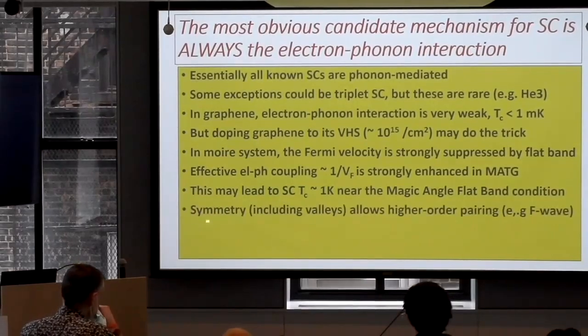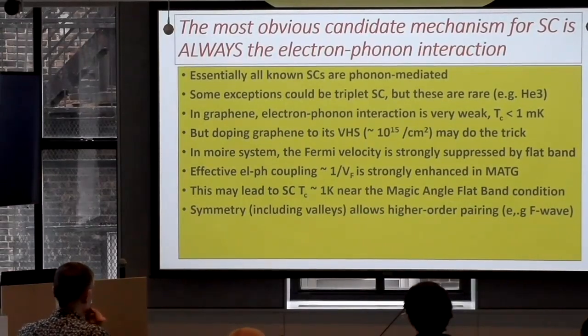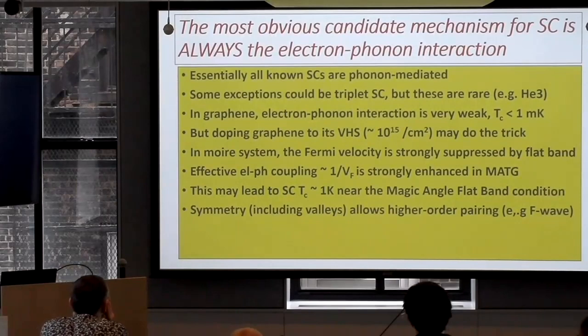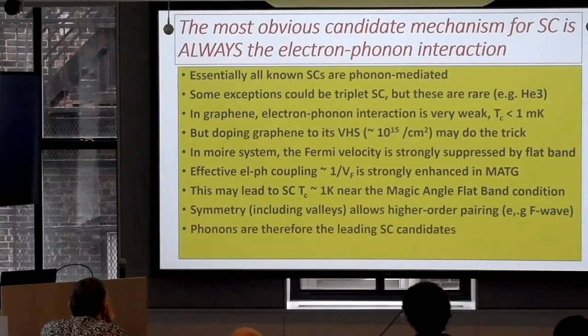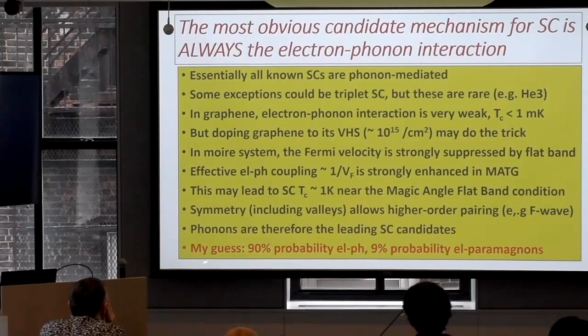Now, since you have symmetry, including valleys, you can have higher order pairing. Normally, electron-phonon interaction just gives s-wave. But here, as I'll show you, there could be degeneracy between s-wave and f-wave. The original argument was you cannot get higher order superconductivity, but now we know that it happens, okay? So it's a candidate. My current belief is that there are some situations, in particular Bernal bilayer graphene, where it probably is electron paramagnon, but the rest are electron-phonon. I'm not very happy with that. Two mechanisms come in. If two come in, it's possible others come in also. So the question is open.